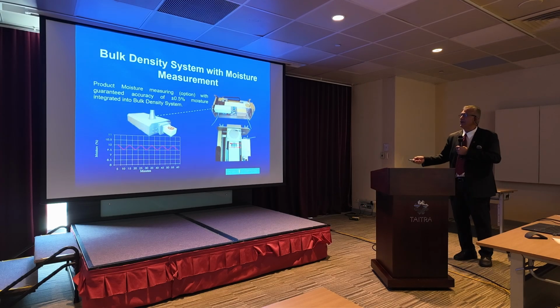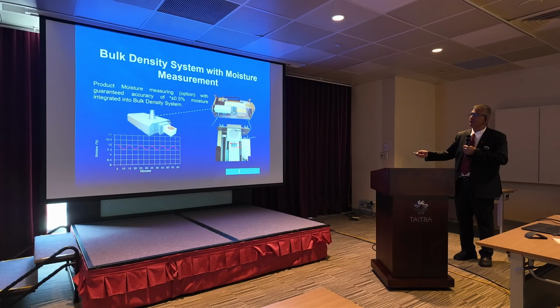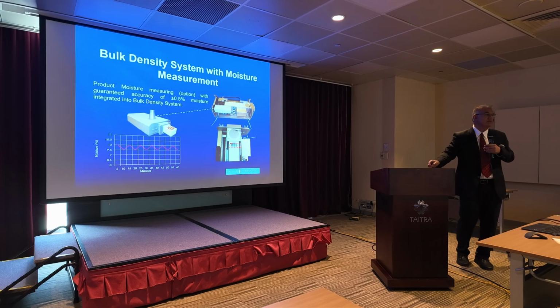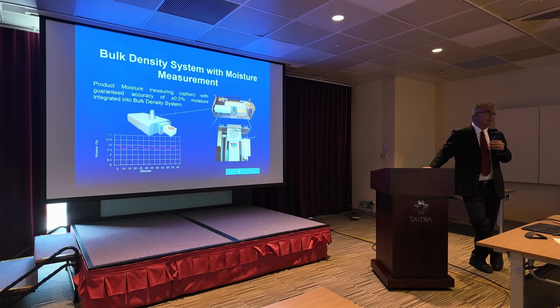Therefore, basically, you have different kinds of systems. It gives you 0.5% moisture variation. You can do bulk density and moisture measurement at the same time. Therefore, you don't want to dry too much in that dryer. What happens when you dry too much? Even 1% extra drying, you are going to lose a lot of money, because you are selling pet food at 10% moisture content in the US, 9.5 for 10%, and you're drying 1% extra. You don't realize that drying 1% extra, at 10 tons per hour, you calculate you're losing 1% extra per hour, per day, per shift, per week, per month. You're losing a lot of money.